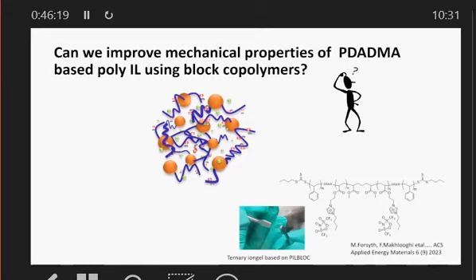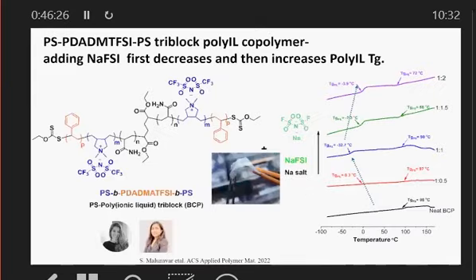And that's not as easy because the chemistry is different. The acrylate chemistry is quite straightforward to control molecular weight. Nevertheless, Antonella, who was working with David's group, she's now at Tecnalia, but she worked in David's group at the time, and my then student Sneha spent some time at POLYMAT, and they did make a polystyrene tri-block with this polyDADMA, although we couldn't get very high molecular weight polystyrene. So the material is okay. It's not brilliant, but it is okay.